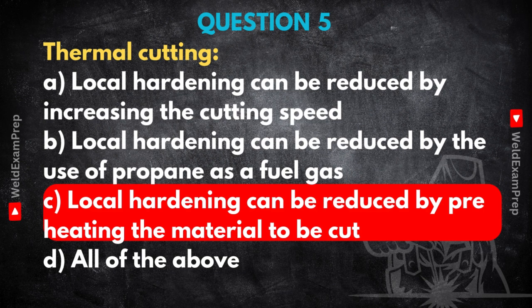That slower cooling gives the steel's microstructure time to transform into tougher, less brittle phases, like pearlite or bainite, instead of that hard martensite. You're essentially managing the cooling curve. So preheating is like giving the material a gentler cool down, avoiding that thermal shock that creates brittleness. That's a great way to put it.